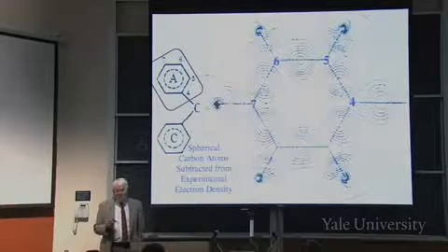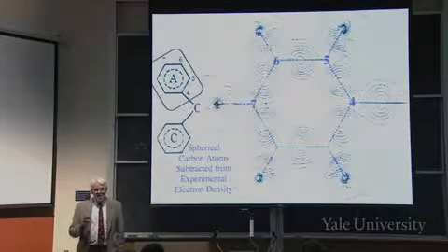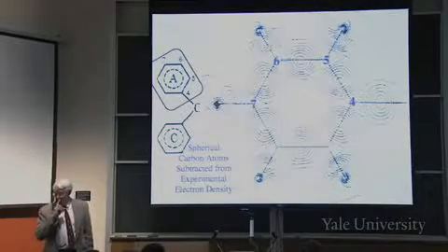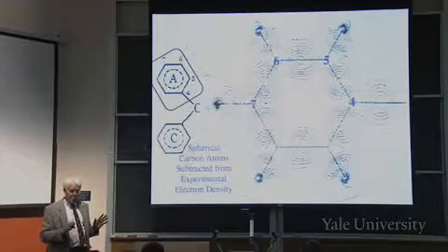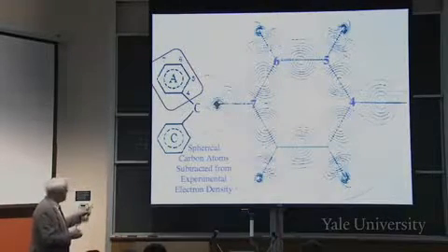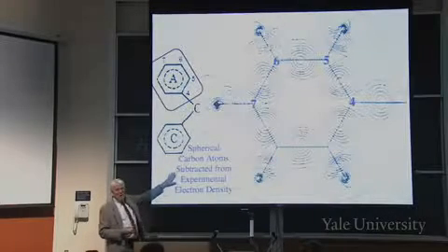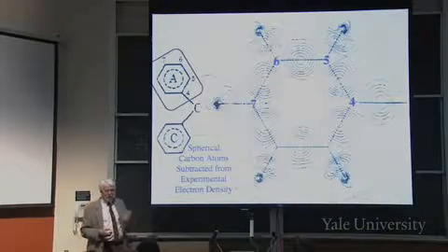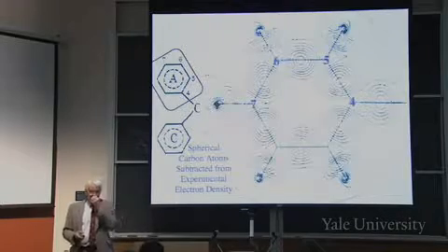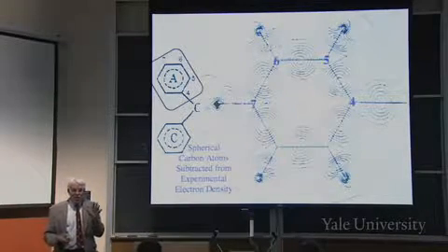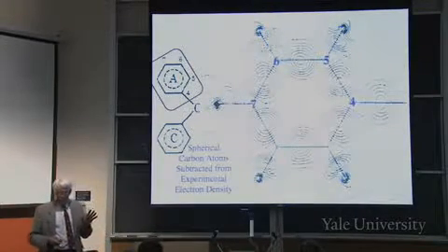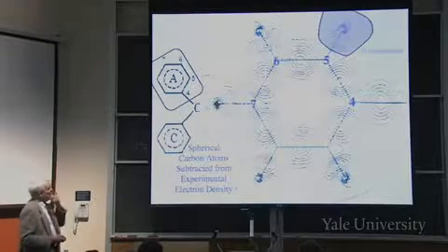Okay, so this map that I'm showing you here is a difference density map. It's the total minus what it would be for the atoms. But notice what was subtracted is just the carbon density. It didn't subtract hydrogens. So let's look at the features that are big here. This is how the electron density changed in forming the molecule from atoms. Okay, so first look up there.